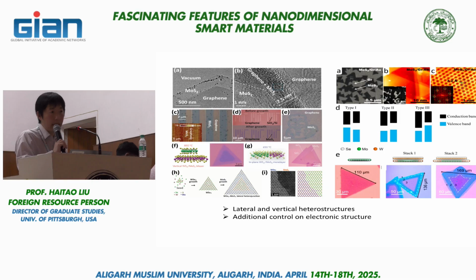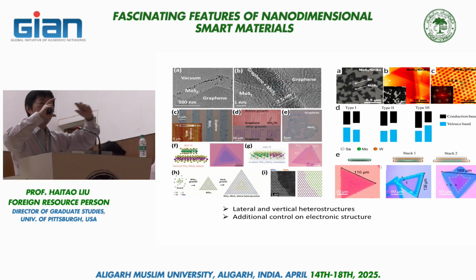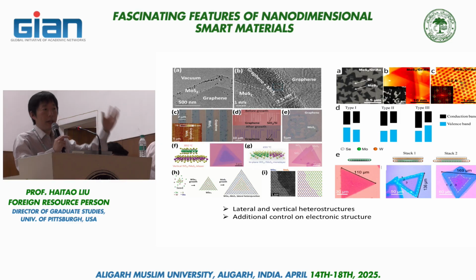Depending on the particular electronic structure, you can have so-called type 1 or type 2 heterostructure, or even type 3 heterostructure, and those are examples shown in this bar diagram on the right-hand side, depending on how the band gaps of the two materials are stacked against each other. If you have one small band gap and a larger band gap material, and they are perfectly aligned in the middle of the band gap, that's called a type 1, and that usually is a combination that's useful for energy transfer to one material.